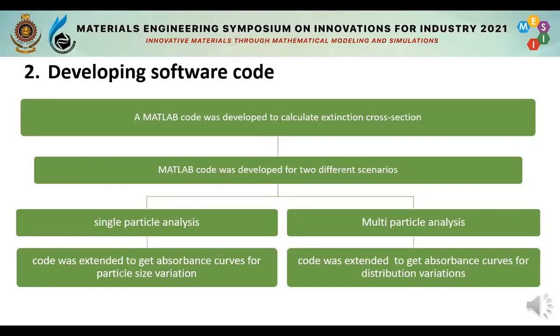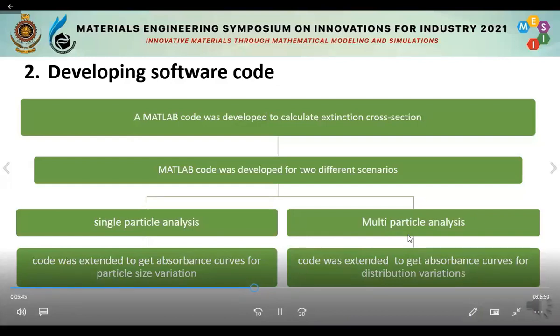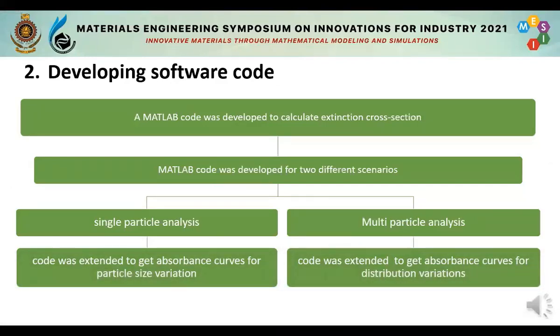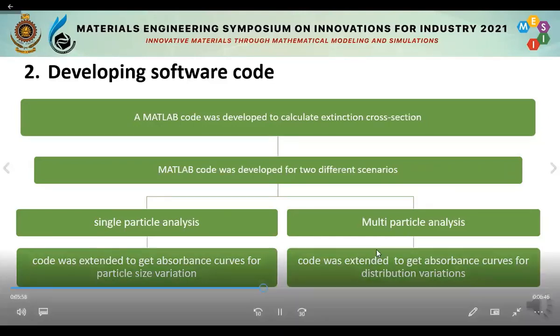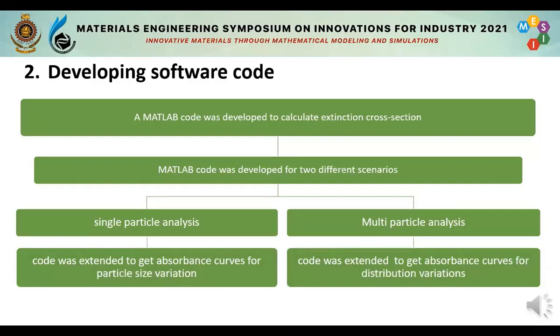Then it was extended to obtain the characteristics of the surface plasmon band for silver nanoparticles, such as how the maximum absorbance changes with radius, how the peak position changes with radius, and how the full width at half maximum changes with radius. Second one, practically it's not possible to prepare a nanoparticle solution with nanoparticles of the same radius. A nanoparticle solution has a particle size distribution. So the MATLAB code was developed to get the absorbance band and characteristic curves for a particle size distribution. Then the deviation between our theoretical result and experimental data could be reduced. Then this MATLAB code was extended to get the absorbance band for distribution parameter variation.